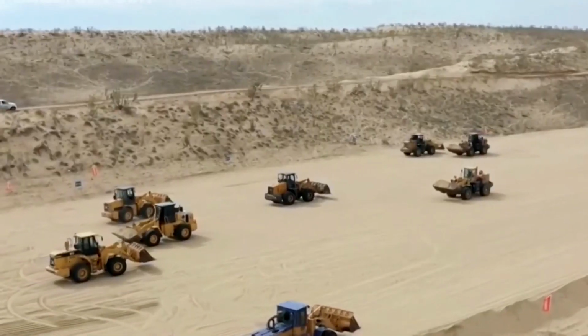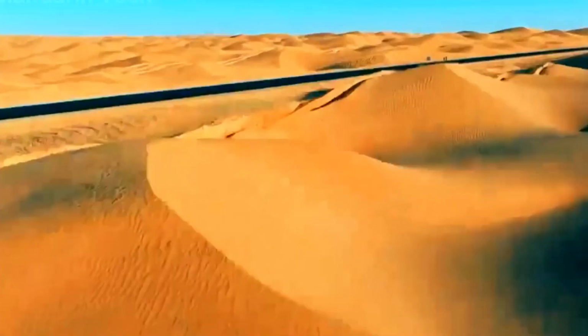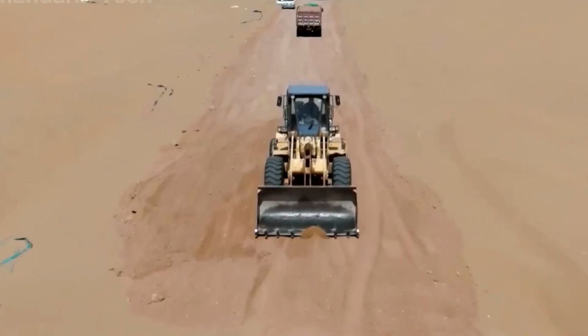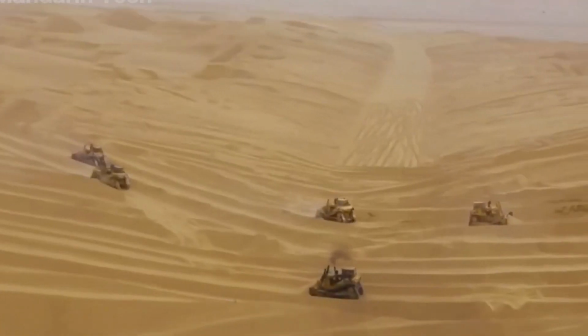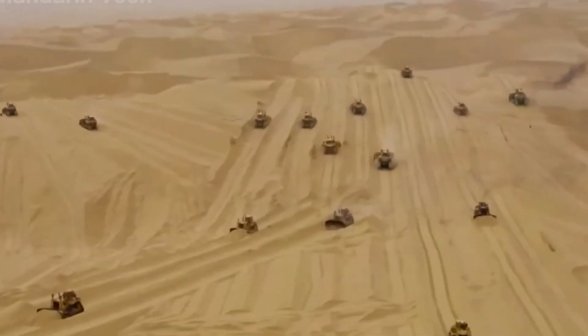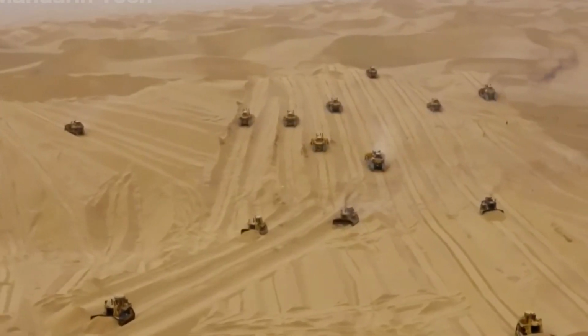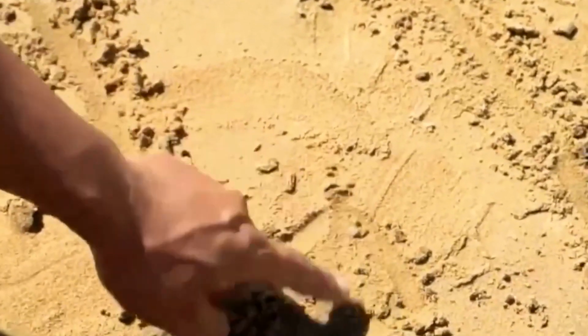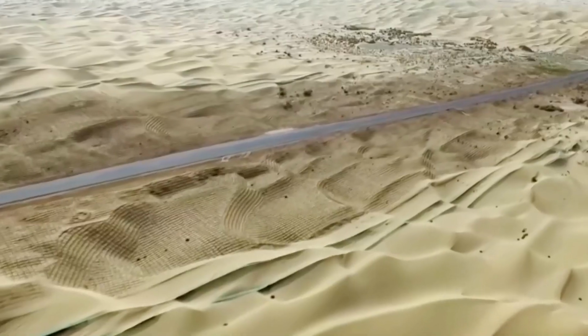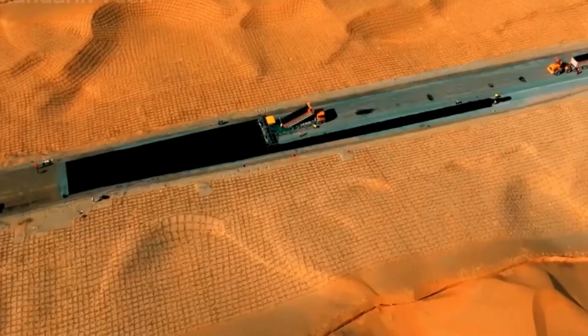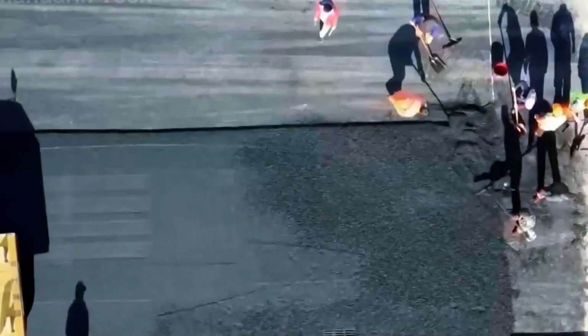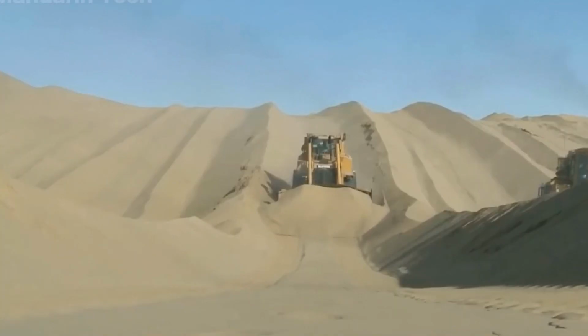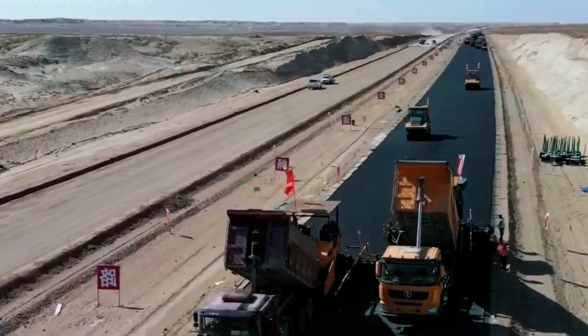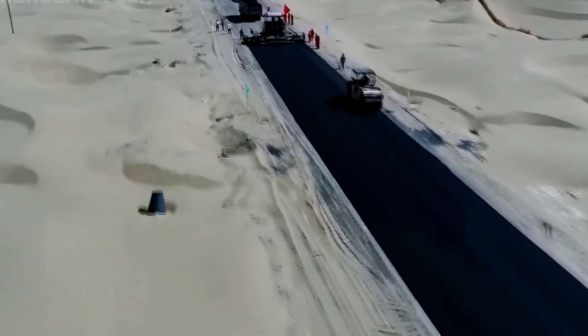It gets more complex further on. Heavy rollers move in immediately after the sand reaches the right level of dampness. It is visible how they compact the surface to remove air pockets and lock the particles in place. The constant rumble of steel drums echoes across the desert as each pass turns soft, shifting sand into a firm, uniform base. By the time the surface dries under the desert sun, it has hardened enough to carry the weight of cranes, mixers, and supply trucks.